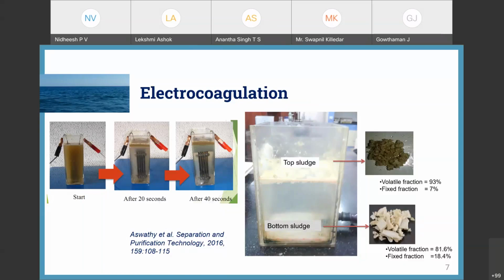So this is, if you are running an electrocoagulation system, you will get these types of reactions. That means if you can see a turbid solution, and if you are running the treatment, then you will get a clear solution after maybe 30 minutes or within 1 hour. You will get good results for this electrocoagulation system. This is one of the studies done by Aswathy et al..